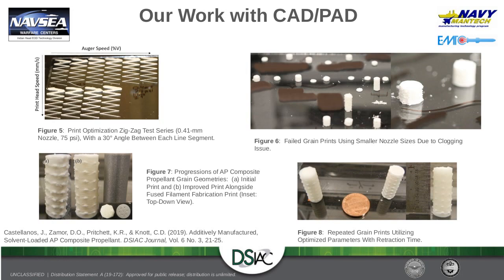We determined that they got mitigated when we used a much bigger nozzle size. We had to choose between three: the 0.2, 0.25, and 0.41 millimeter nozzles. With the 0.2 and 0.25, no matter how much effort you put into scrutinizing every step from mixing to printing, it would occasionally clog up on us. But with the 0.41, even if we were loose about mixing, we always managed to print a full grain. So yeah, that was a good question.